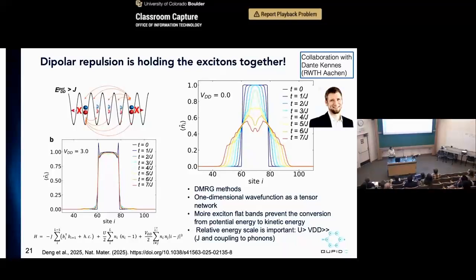And this is because the energy scale of dipolar interaction is larger than the energy difference between different Moiré bands. So these Moiré bands are very flat, right? If the energy scale of dipolar interaction is larger than the energy difference between these bands, in this case around 3 meV, then it's very hard to dissipate that energy. Of course, you can always say, okay, let's use phonons, but it turns out that phonon scattering is probably slow at this very low temperature. So the conclusion that we got from Dante's calculation was that this dipolar interaction, because the energy scale is still much larger than J, and also the coupling to phonons, kinetically prevents the melting of these Mott states.